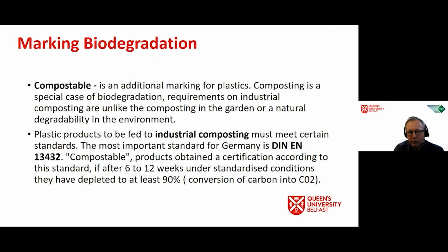So then just to touch on biodegradation and marking biodegradation on the final product, although this is not really about the final product, but I thought I'd just mention this. For the end user, there is marking for biodegradation, and in particular composting. And if products are going in industrial composters, they must meet this DIN standard 13432 compostable certification, which states that after 6 to 12 weeks, they will have depleted to at least 90%, and this depletion means the conversion of the carbon into CO2. It's not a weight, it's actually a chemical conversion of the carbon into CO2. So it doesn't mean more than 90% by weight.